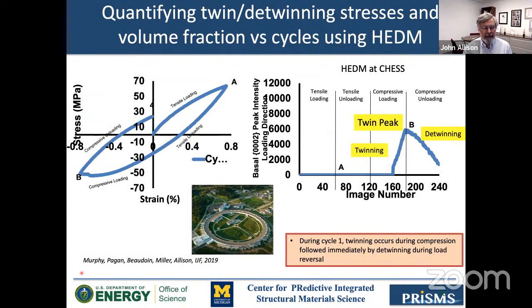So we started looking at this using synchrotron research at CHESS. And this is the work of Ariel Murphy, now Leonard. She was a student in the center, and is now at Ohio State. Ariel did high energy polycrystalline diffraction of these tensile fatigue samples, and this is basically looking at this twin peak. There was no activity until we got to a certain compressive load, then we reversed the load and we saw detwinning. So she could qualitatively understand twinning and detwinning. We could relate this directly to a compressive stress and a tensile stress over here. So we could quantify the twinning and detwinning stresses. However, the volume fraction is more problematic using this particular HEDM technique.